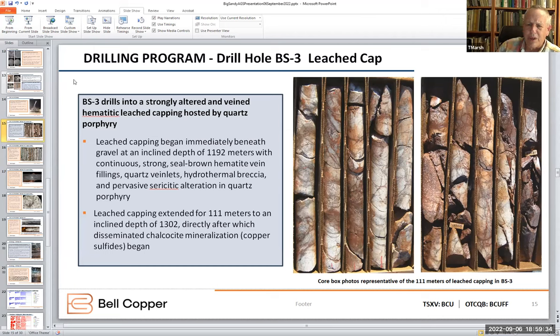So I watched this come out of the ground day after day, about through Thanksgiving of 2021, dreaming what might be causing that hematite. I have an X-ray fluorescence analyzer, which I would hit that hematite with all the time, and really saw very low copper numbers, 50, 60, 70 parts per million copper in the earthy hematite, but it looked like fertile hematite to me, so we kept drilling.